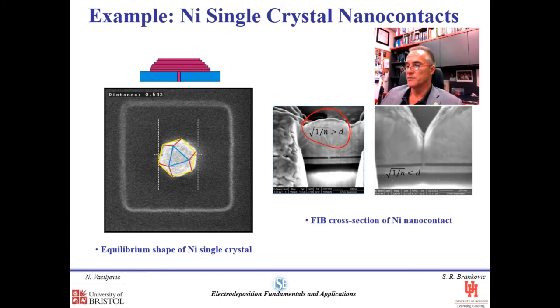We can also drive the process in a different way, where the average separation between the nuclei is actually smaller than the confinement of the electrode. In this case, interestingly enough, we can have two nuclei, which is shown here, which can form a twin. And if we increase the deposition flux even more, we can have more than two, three or five nuclei within the boundary of the nano-confinement, and we can have a polycrystalline deposit. For many applications, when we come to nanostructures, single crystallinity is preferred.